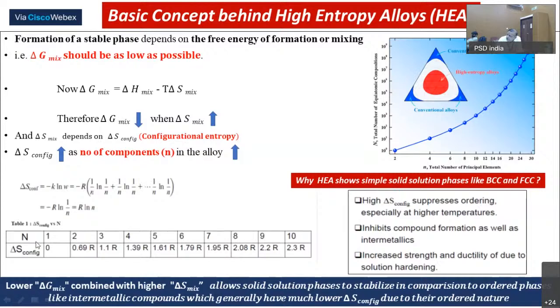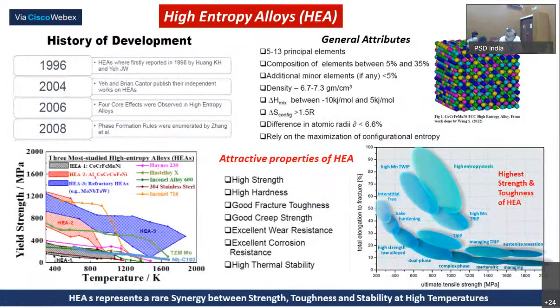But from a phase transformation point of view, let me draw your attention toward this triangle. Conventional alloys generally probe the edge of any phase field. In a triangular phase field, they generally probe only the corner part, whereas high entropy alloys hit right into the center of the phase, and that is where they achieve the high entropy. So in the process, we are increasing the strength without compromising too much on the ductility, and that could be the new alloy system.